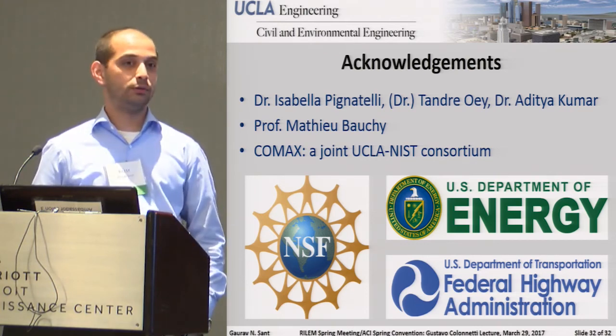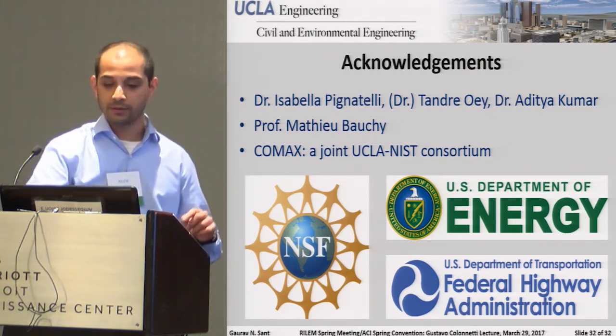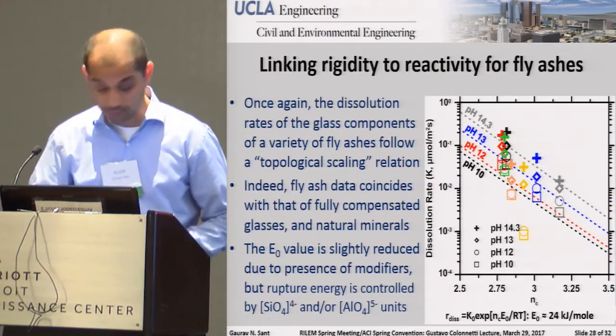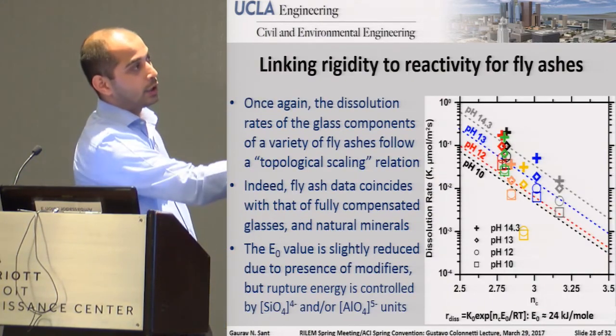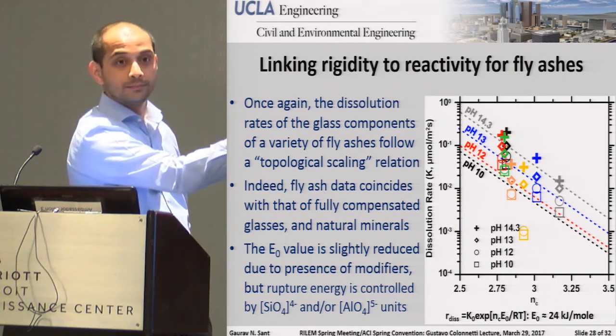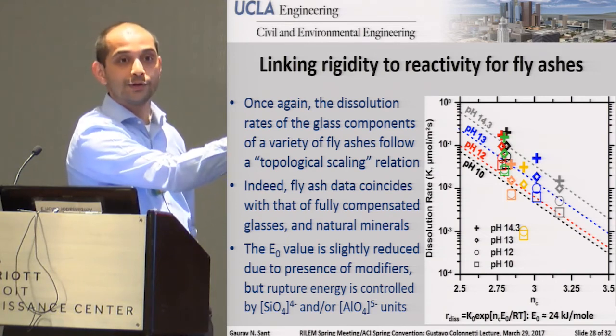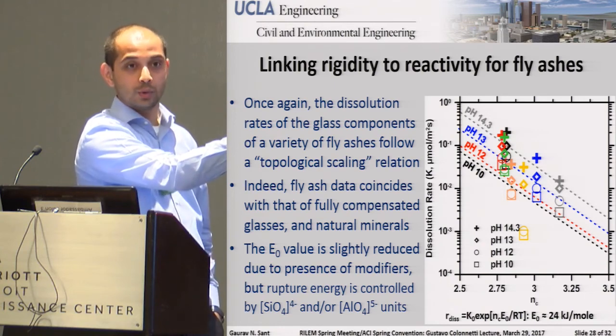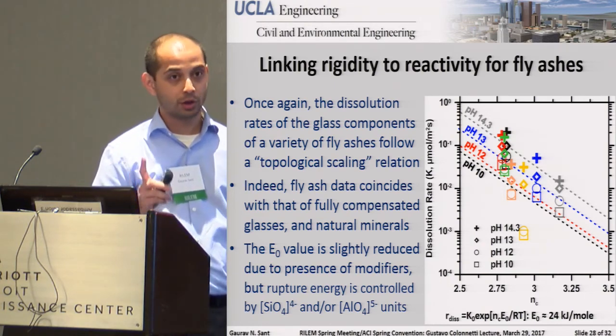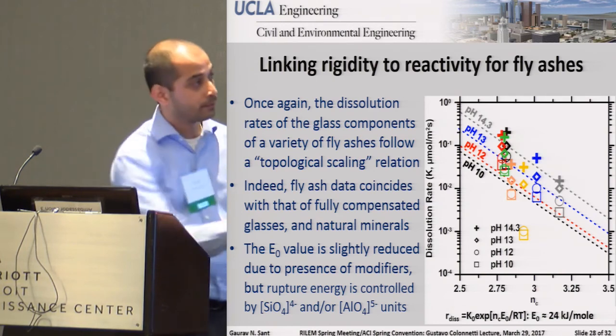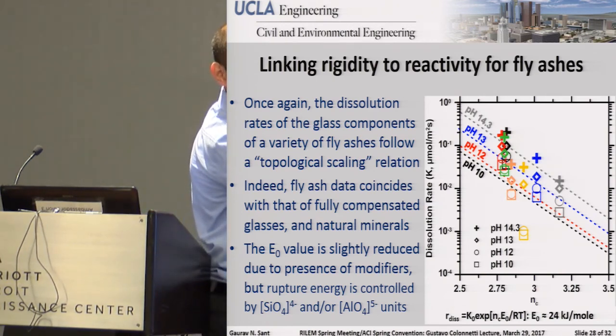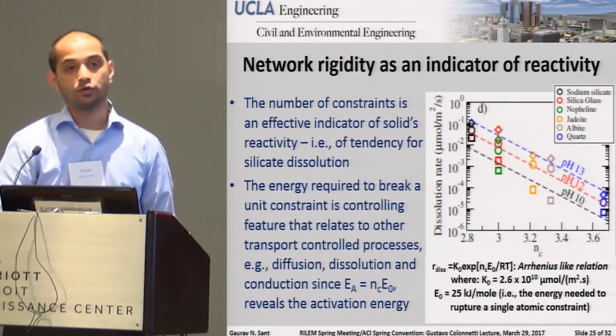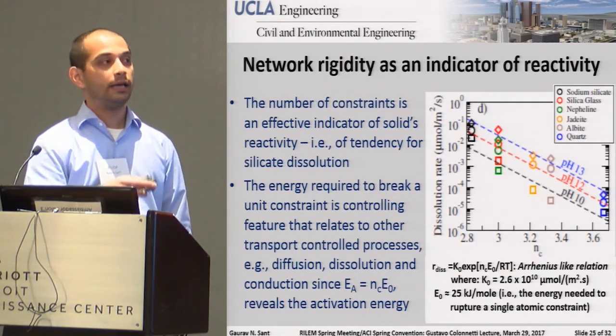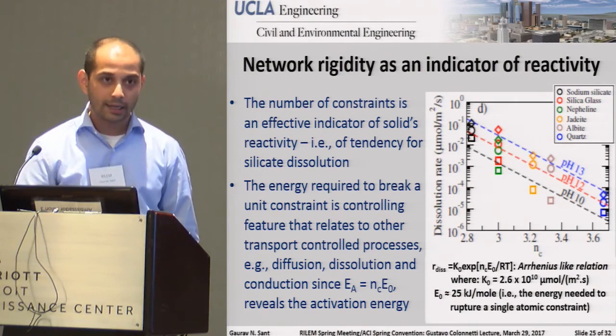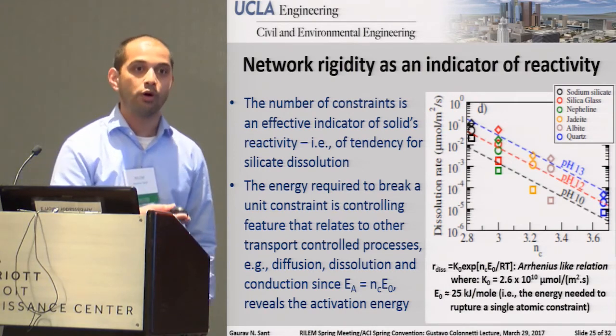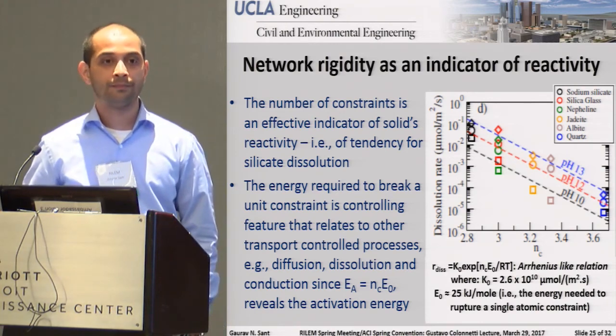Okay, so basically it has no influence. pH makes a difference insofar as, as you increase the pH, you increase the rate. But as you can tell, these lines remain perfectly parallel to each other. Because they remain parallel, what that suggests is the value associated with the rupture energy does not change. Rather, what is changing is the pre-exponential number right here. So that's really the thing to point out. Of course, while pH does increase dissolution rates, in the context of analyzing the data and developing the framework by which you can analyze this, it has no impact.